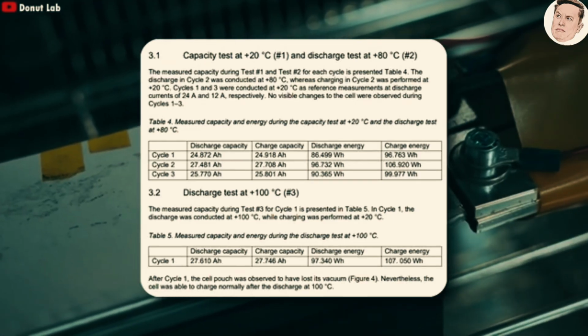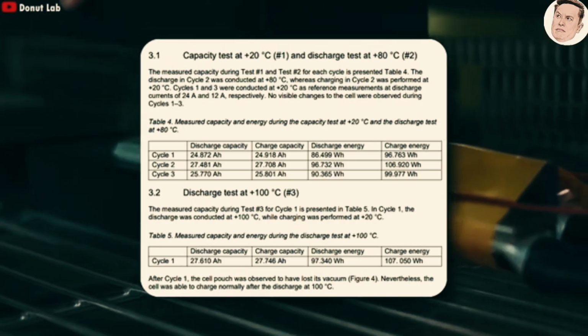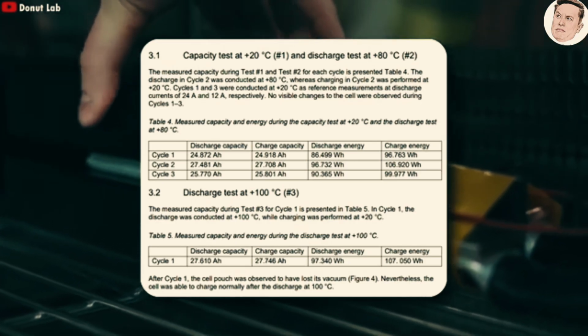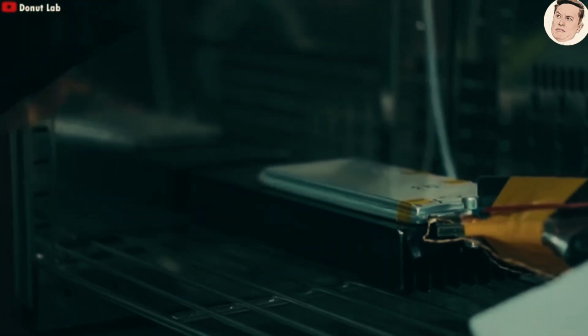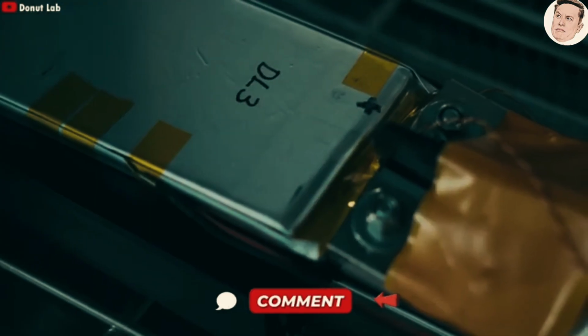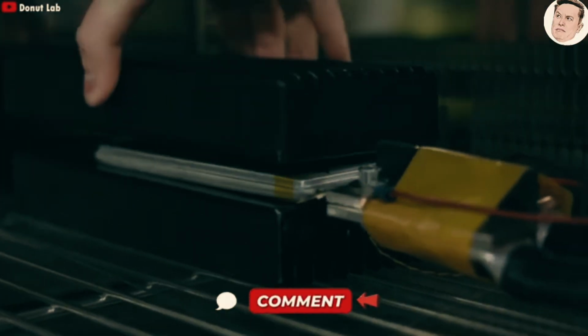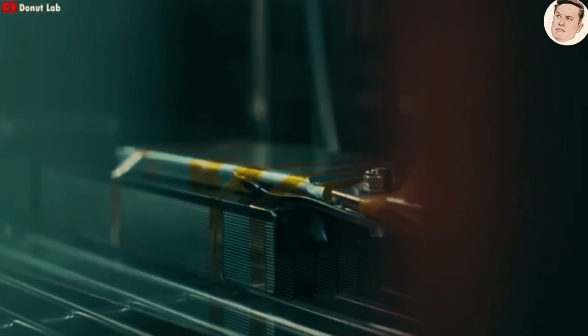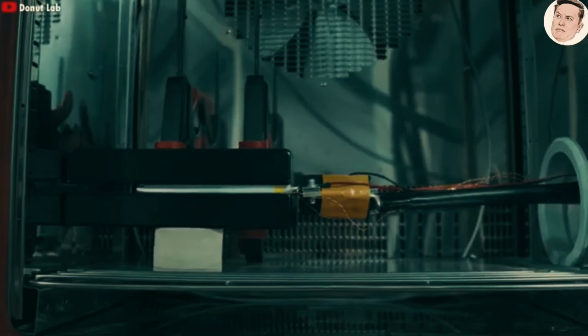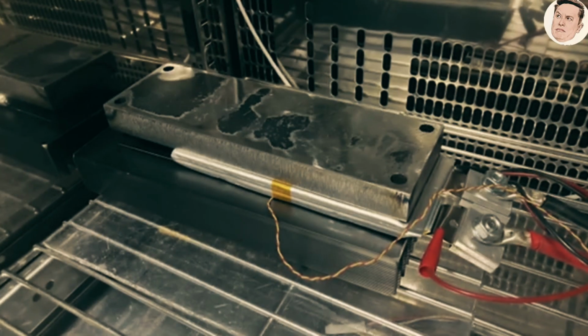Basically, the 100 degrees Celsius test was conducted at a 0.5 C rate, only half the rate of the 80 degrees Celsius test. So the two figures cannot be directly compared. What is quite interesting is why they did not test at 1 C at 100 degrees Celsius. We do not fully understand this. If you have an explanation, please let us know in the comments below. However, there is one notable issue. After discharging at 100 degrees Celsius, VTT observed that the battery pouch had lost its vacuum. The battery was still functional and charged normally afterward. But the outgassing suggests that either the packaging or the battery's chemistry generated gas at that extremely high temperature.